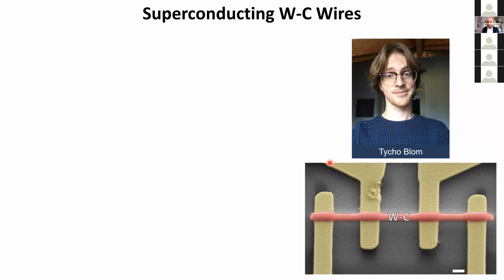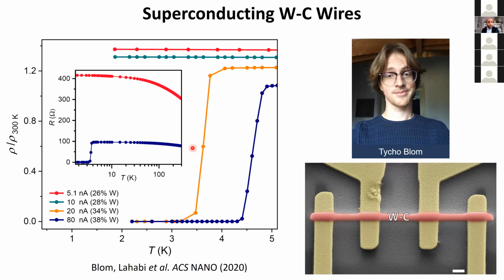than the previous reports. So in the previous reports that I showed you in the previous slides, if you want to do EBIT, you usually go for something in a picoamp region, like let's say 10, 20 picoamps or 100 picoamps max. But here actually Tycho is using, for the first wire, 5 nanoamps. And then of course, for the next month or so, we started to optimize both the beam current and other parameters. And at the end, we managed to get superconducting tungsten carbide with a transition temperature of about 4.5-5 Kelvin, which is a relatively comfortable temperature to work with, at least for experimentalists.